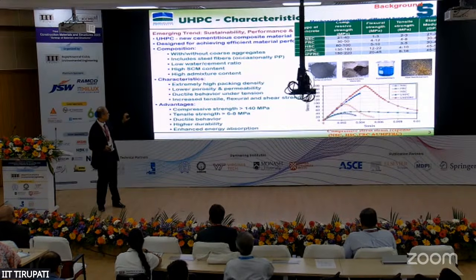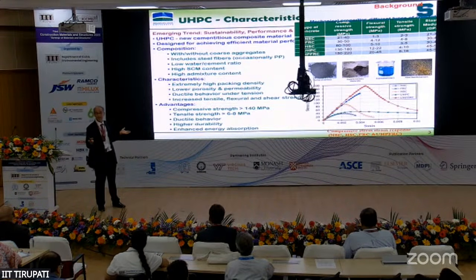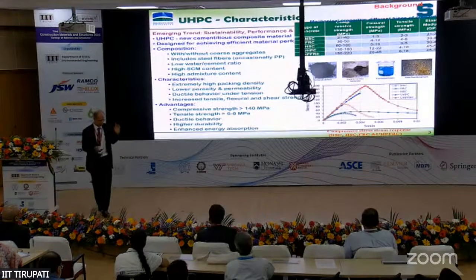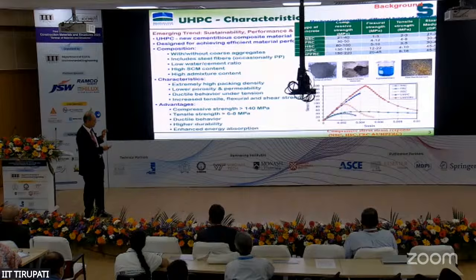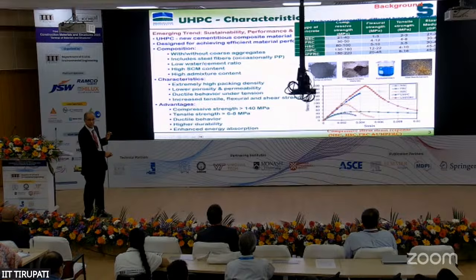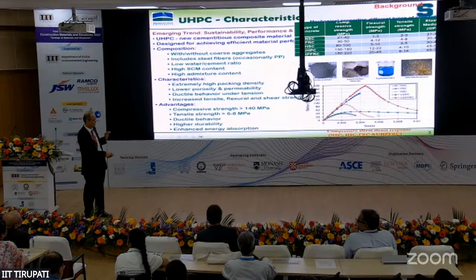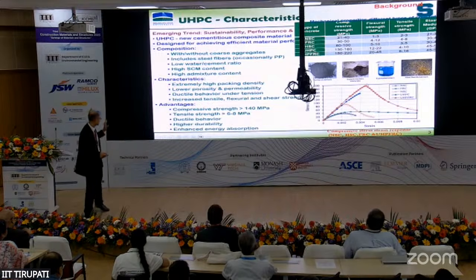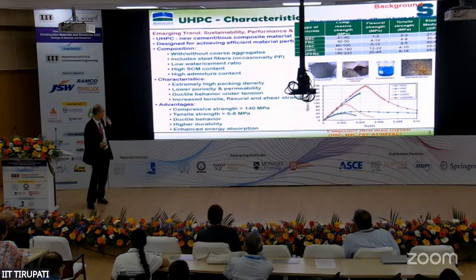When you do this, its characteristics are very high packing density, as you know, compared to your conventional concretes, low porosity and permeability, and you get a very ductile response if you add those steel fibers, right? Strength is higher. You see this regular concrete here. If you add steel fibers, your strengths are much lower here, but it's ductile. But with UHPC, you can get much higher strengths and ductility, whatever you need.